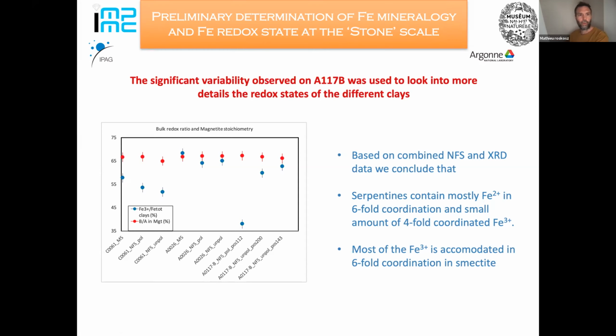If we look at samples like C61, that is very rich in smectite, the QS and IS are a bit different, and we end up with 6-fold coordination for both iron 3+ and 2+, which is typical of smectite, and which also suggests that maybe the iron 3+ is formed by oxidation of the iron 2+ during metasomatism or fluid percolation on the Ryugu asteroid.